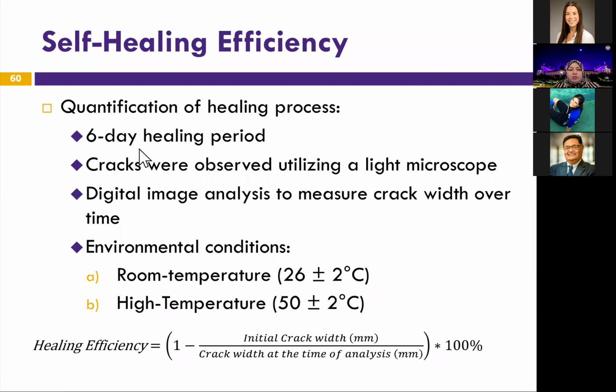The healing process took place over 6 days. We looked at the crack size using a light microscope on a daily basis. And we put the specimens in two curing conditions, room temperature and high temperature, which is 50 degrees plus minus 2 degrees Celsius. And we calculated the healing efficiency.